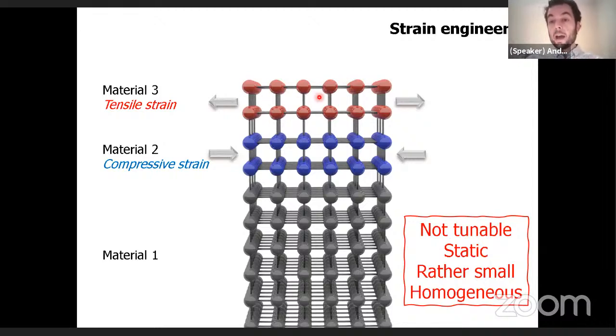But this approach to apply strain is not tunable. Once you force this epitaxial growth, you cannot change it—it's static. If you're thinking about exploiting strain engineering to fabricate a functional device, you want something you can change in time. Also, this approach usually yields rather small strains because these three-dimensional materials are typically brittle, and usually it's homogeneous across the wafer scale.